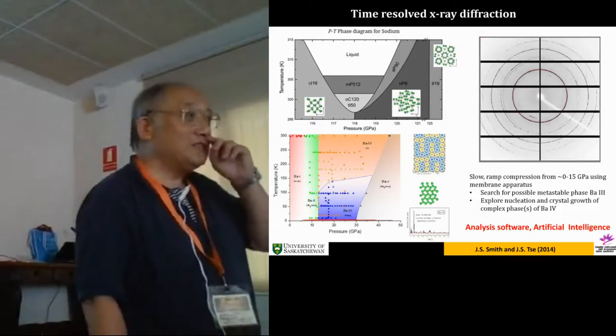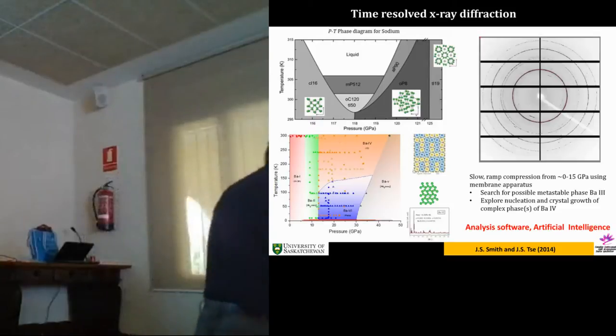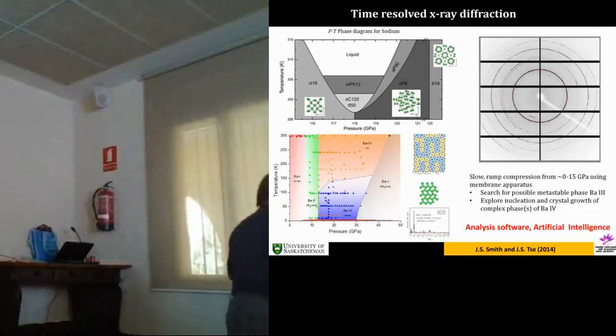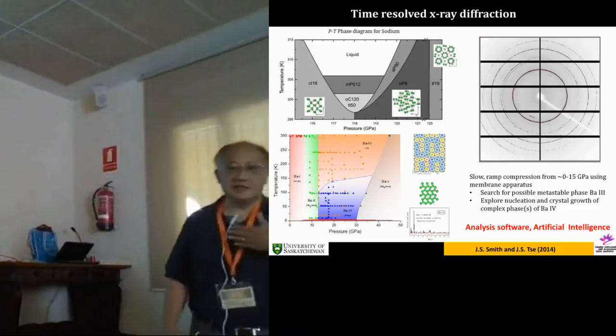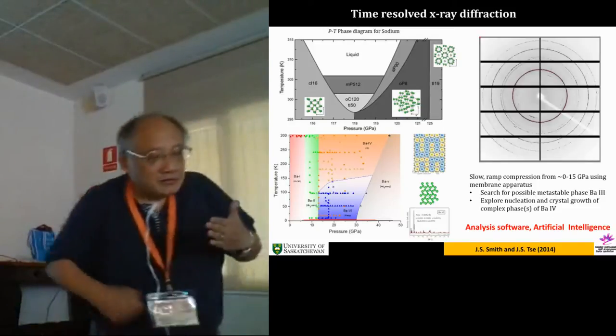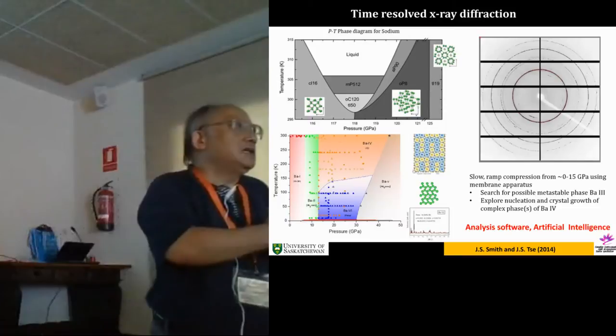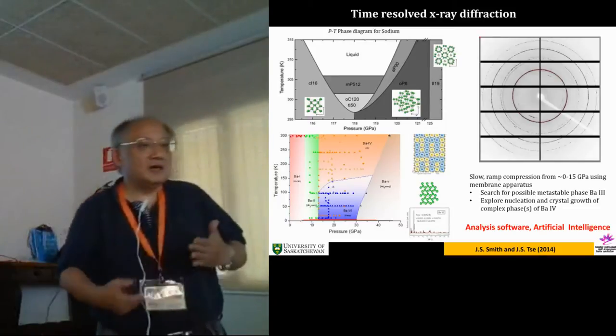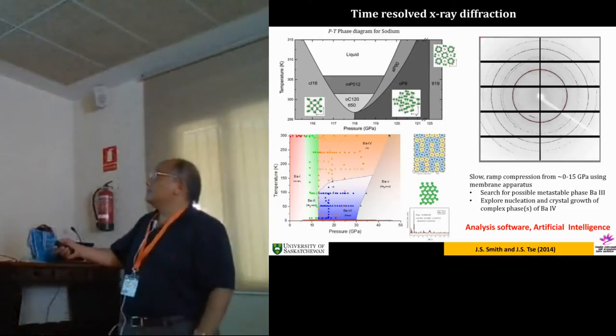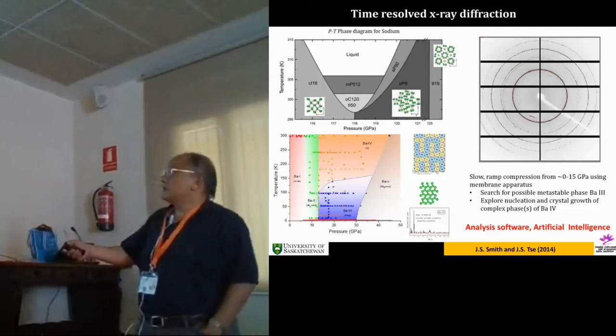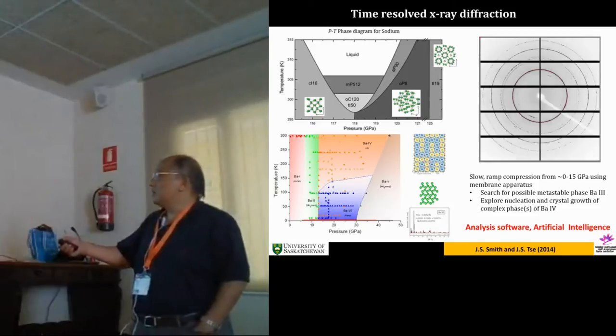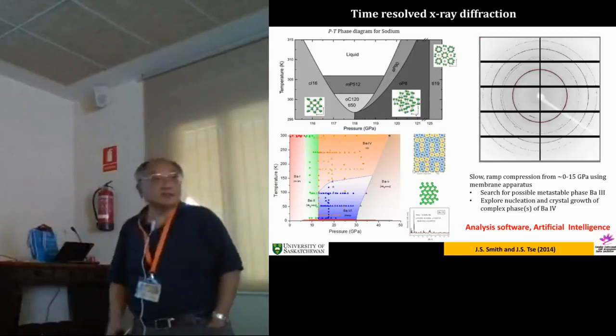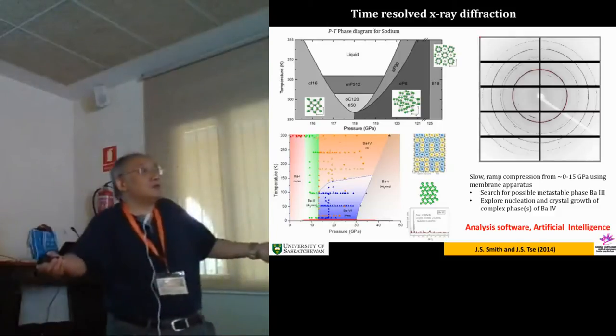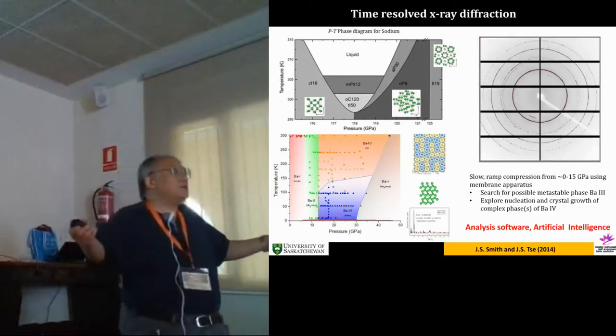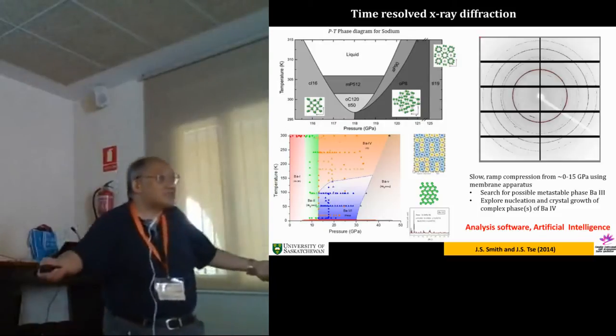So one thing they didn't talk about here is time-resolved X-ray. I think most synchrotrons are now very active on time-resolved X-ray. The reason is that with this technique, you can actually increase pressure continuously, and you can control it. So why is it so interesting? You look at sodium, the cI16 phase was mentioned yesterday, and then when you compress it, it becomes more and more complex phases. So how does it occur? Can I map out the kinetics? Can I map out the intermediate states?